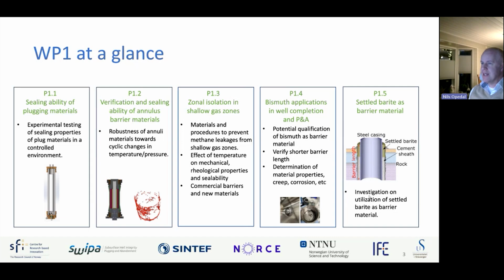Yep. So again, a quick glance at WP1, we're not going into full detail here. We have 5 sub packages. Package 1.1 deals with isolated cement plugs, meaning cement plug inside casing, experimental testing. Package 1.2 deals with annular barrier materials, and then we have package 1.3, more specific towards isolation in shallow gas zones. Package 1.4 deals with bismuth as a new material, and package 1.5 deals with settled barite to be potentially used as a barrier material.